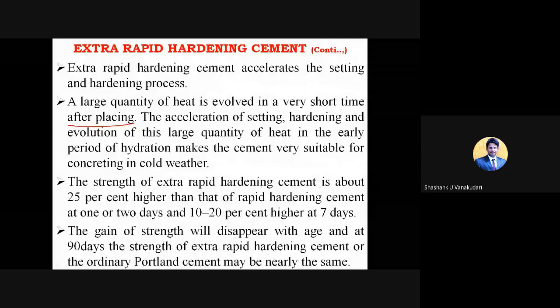And here the strength of the extra rapid hardening cement is about 25% higher than that of the rapid hardening cement. Here, only the rapid hardening cement is going to get the high early strength. Clear? But when you use this extra rapid hardening cement, it is going to give around 25% additional strength. Yeah, 25% higher than that of the rapid hardening cement at 1 or 2 days, and 10 to 20% higher at 7 days.